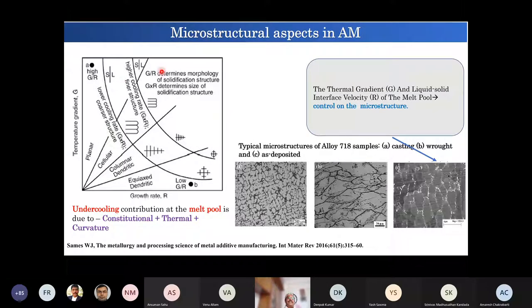And this is decided by the ratio of thermal gradient divided by growth rate, which determines the morphology of the solidification structure, and the product of these determines the size of the solidification structure. So this is a very favorite diagram for many people, and in our discipline, many people are working on generating such a diagram for different materials. And then of course the next step is, what are the consequences of these microstructures?